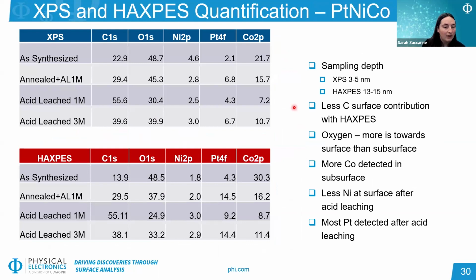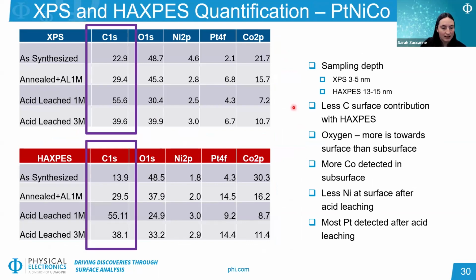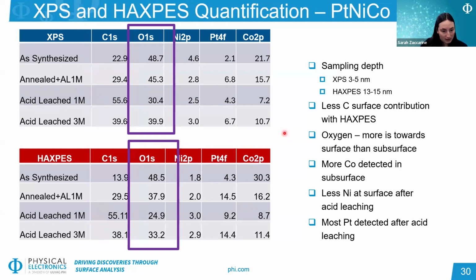Again, we can look at the quantification with these techniques, and we see similar trends as before, where we have less carbon detected in certain samples with the HAXPES source. We see some differences in the carbon amounts with the post-processing steps. It looks like the annealing step does impact the amount of carbon that was detected, and these ones that did not have annealing, there was a much higher carbon concentration, both at the surface and subsurface after acid leaching. With the oxygen data, we see more similar amounts for the as-synthesized sample at the surface and subsurface, but we see some changes with post-processing, again with these two acid leaching steps having some differences from this additional annealing step.